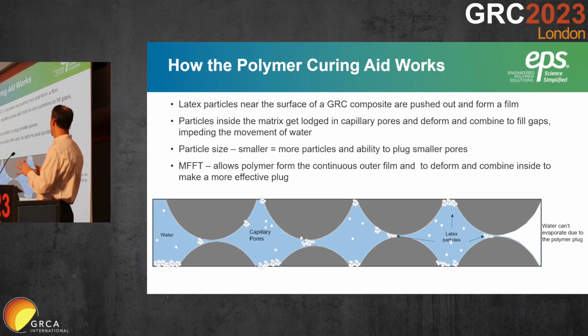So how it works. I've got the marvelous art there, displaying the capillary pores and water in there. First of all, you've got two things that happen. As the cement cures, there's less space for the polymer and the water to be in, so it pushes some of those out. And when the polymers come to the outside, the water evaporates, the polymer can't, and those polymers will coalesce, basically forming a film on the entire outside of the surface. So you've essentially encapsulated the whole GRC panel piece with a semi-permeable membrane.